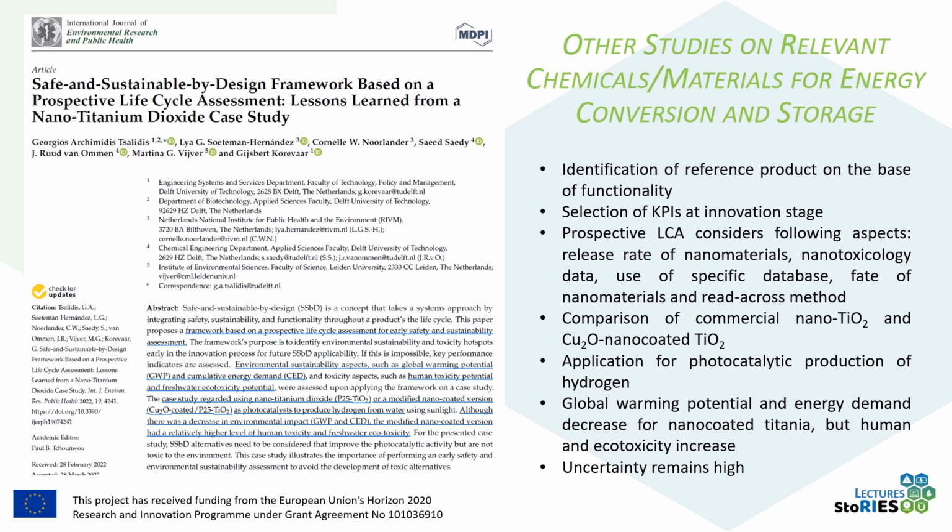The application was for photocatalytic production of hydrogen, and some specific results they got are that the global warming potential and the energy demand decreased for the nano-coated titanium, but the human toxicity and also the ecotoxicity increase. However, the authors also put in evidence the fact that for these materials the uncertainty remains quite high.